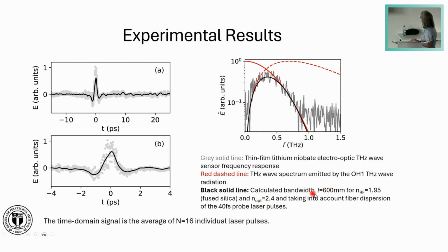the MZI arms were, this is a typo, 600 micrometer, where we had a fused silica substrate, and the optical index of refraction was 2.4. We also took into account the dispersion of the 40 femtosecond laser pulse in the fiber. So we found quite good agreement between the expected frequency response and the measured frequency response.